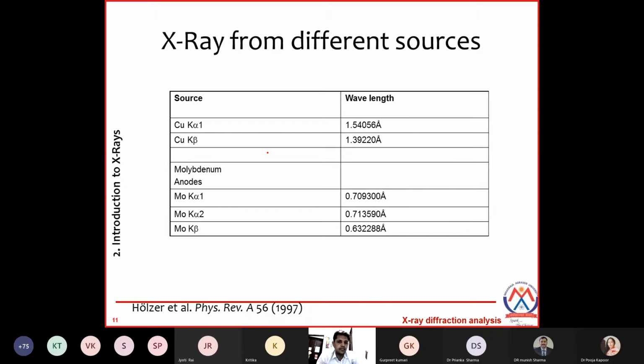Copper has two peaks, K alpha and K beta. K alpha is in the range of 1.54 Angstrom or 0.154 nanometer, and K beta is 1.39. In most cases we use K alpha. As far as I understand, I never came across any XRD equipment where we use some other type of source. So copper is the most widely used metal to produce X-ray for an XRD diffractometer. Then there is molybdenum also. Molybdenum gives you a range of 0.7 Angstrom, 0.71 Angstrom, and 0.63 Angstrom.